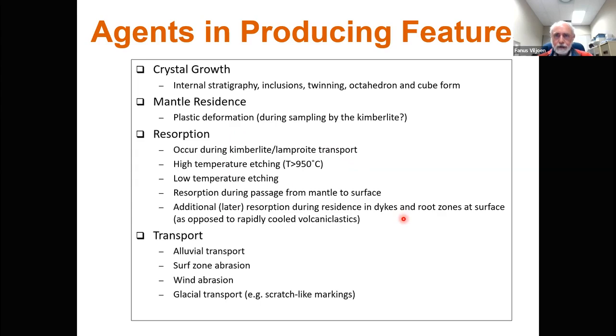And then if your diamond is sitting in a root zone, for example, or a dike, which takes a bit longer to cool down relative to rapidly extruded volcanic clastics, you will see other surface textures that form. And then finally, if there is transport within the surface environment after the diamond is released from the kimberlite, you have things like alluvial surface textures of surf zone abrasion, wind abrasion, or for that matter, maybe scratch-like markings in the case of glacial transport.